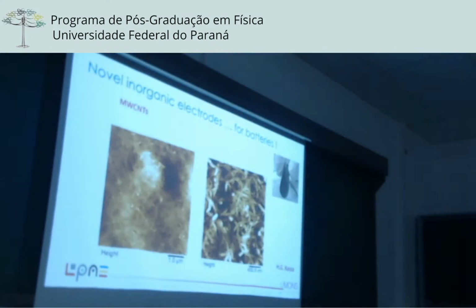Okay, I told you that I skipped this. And then just a microwave impedance microscopy, as I showed before. We have 3 gigahertz. We are measuring the reflection here, and we are using some electronics to decipher the amplitude and the phase. You can see the evolution of the capacity or the resistivity, and you can map the different properties on the flake sample there.